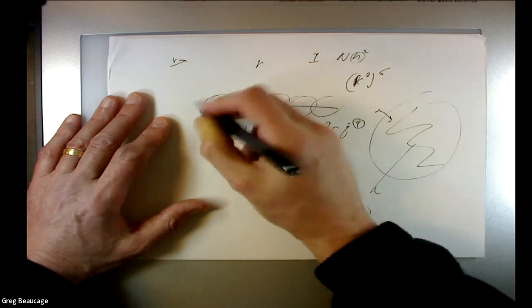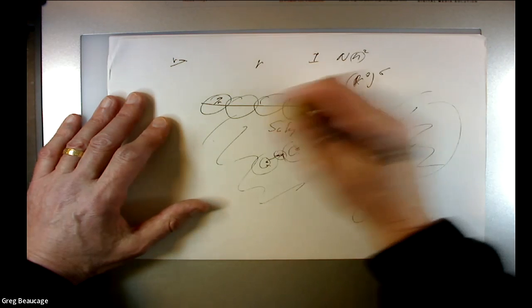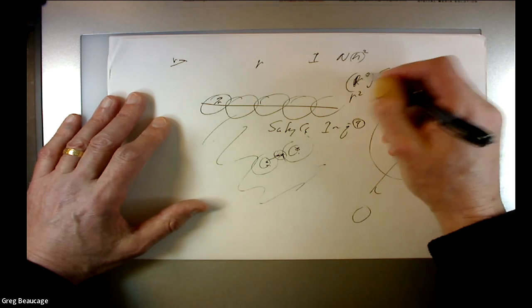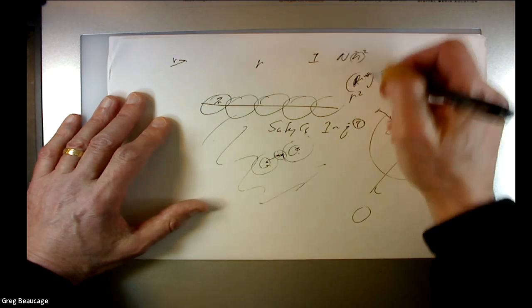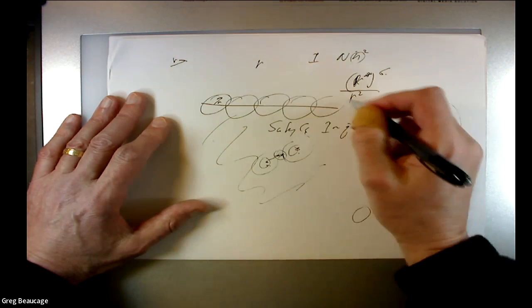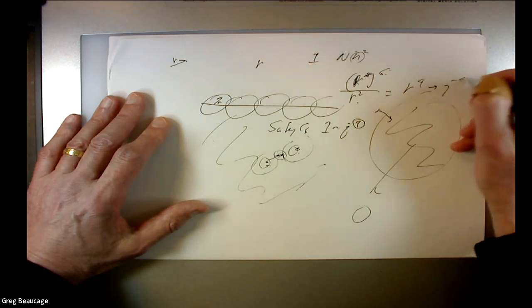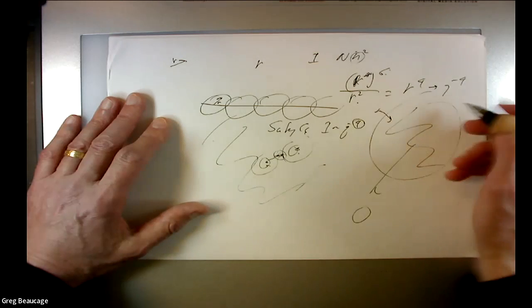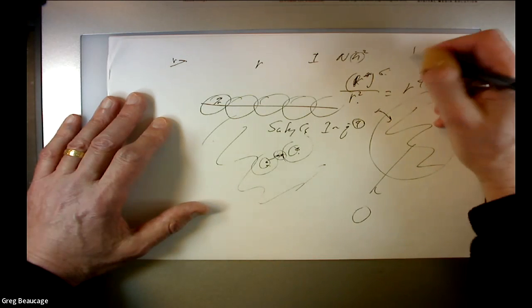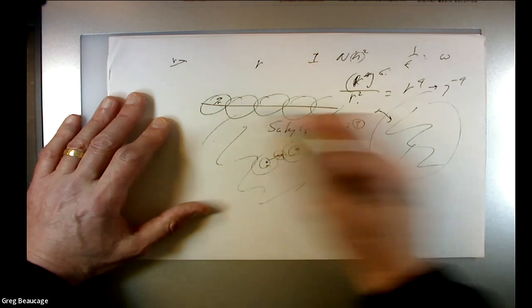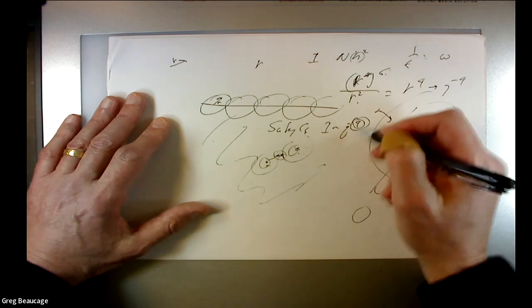And how many of those is going to be 1 over the surface area, which is r squared. So cubed squared gives you 6, the number on the surface gives you -2, so that gives you r to the 4. The transform of that is q to the -4, like an inverse, like frequency goes with 1 over time. So you can just construct that you would get this -4 power law.